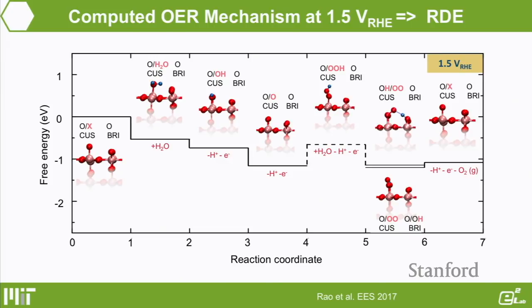So this is essentially combining single crystal electrochemistry, in situ diffraction, and DFT studies. We can actually provide an atomic level understanding of what could be the active site. Essentially, the Cus site is the active site. At the Cus site, you initially have water adsorbed, and gradually you deprotonate to OH and O, and then become O2, and then evolve oxygen. Where the bridge site essentially goes from OH to O, and it becomes poisoned. Essentially, it becomes inactive under oxygen evolution conditions on the surface. So for this surface, only the Cus site is the active site.